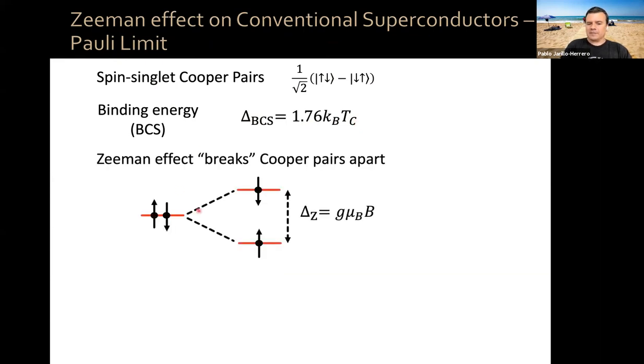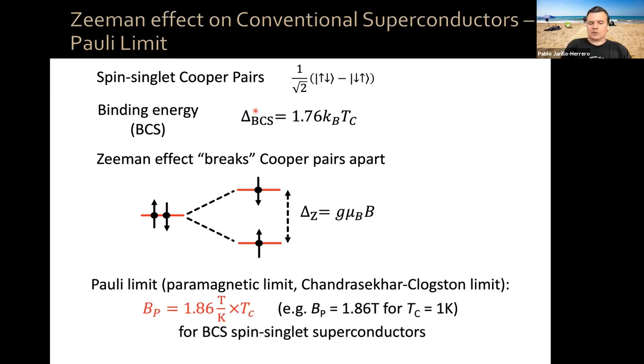A Zeeman effect splits apart your Cooper pairs, okay? So when the Zeeman energy, μB·B, is equal to your gap, then your superconductivity should be long gone. That leads to something known as the Pauli limit, paramagnetic limit, or the Chandrasekhar-Clogston limit, which tells you the critical field for a Zeeman field should be about 1.86 Tesla per Kelvin times TC in Kelvin, okay?